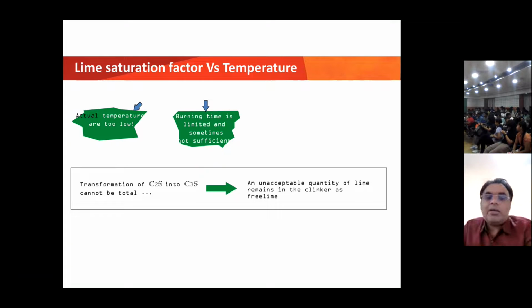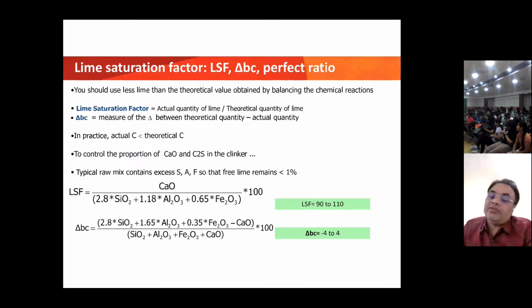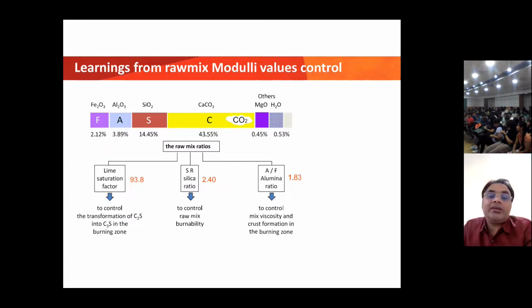This is the LSF formula, which is applicable based on certain scientific notations. We have identified why this factor should be taken and what the range should be. Similarly, for iron, what should be in the iron range, and CO2, whatever you are looking at, is your calcination, right? The lime saturation factor, LSF, which I was talking about, is the transformation of your C2S into C3S, right? Similarly, the silica modulus controls the raw mix burnability, and this is the range. From where it is coming, you can see in the upper side, it is written silica 14.45%, right? And A upon F, the alumina upon iron ratio, controls the viscosity, and it is also used for the liquid formation for the nodulization of your clinker, which can finally be used in your cement grinding to make your cement.